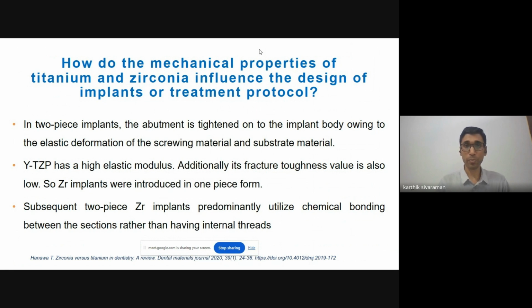For instance, we mostly practice two-piece implants. And in two-piece implants, the abutment is tightened onto the implant body. And that is possible because of the elastic deformation which is happening within the screwing material as well as the implant body substrate. So if it's a titanium two-piece implant, both the screwing material and the implant body substrate are of the same material. However, when we are using a zirconia implant, if we use it in a two-piece manner, we know that zirconia has a high elastic modulus. So there will be a greater resistance to such elastic deformation. On the other hand, its fracture toughness values are relatively low, so it can fracture in thin cross sections. So that is the reason the zirconia implants were initially introduced in one-piece form to avoid this weak implant abutment interface. Even subsequent two-piece zirconia implants prefer this interface to be chemically bonded rather than having internal threads for micromechanical retention. So this is one aspect of how a mechanical property will influence the design of an implant.